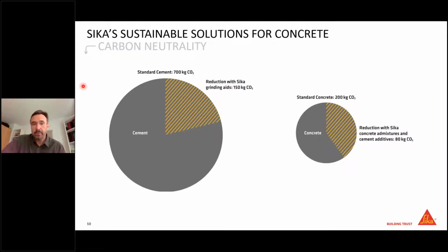So what does it mean, carbon neutrality solutions by Sika? To give you a feeling of the dimension, we are adding just a few drops of our chemicals to concrete. We're talking about, on average, maybe only 5 kilograms per cubic meter. But you see, for the cement production, our grinding aids can already contribute with more than 20% of CO2 reduction. And together with the benefits that concrete admixtures bring, we are ending up at a total potential of 40% CO2 reduction in concrete.